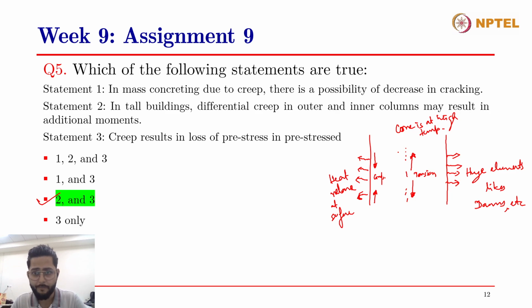So, due to the compressive stress that the concrete is experiencing due to the contraction or the cooling down of the surface, the creep can further increase that cracking due to this compressive stress. On the other hand, the tensile stress due to the heated up core inside the mass concrete structure might result in some kind of cracking inside the concrete structure, because as you know, the concrete is weak in tension. Therefore the thermal expansion will cause a tension, and that will cause a cracking inside the core of the concrete, and due to creep this cracking can further increase.